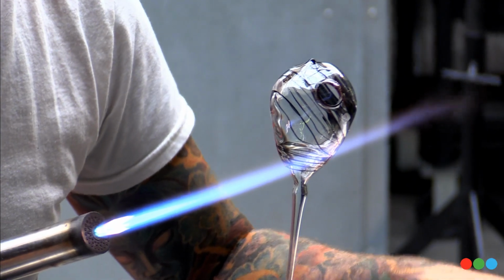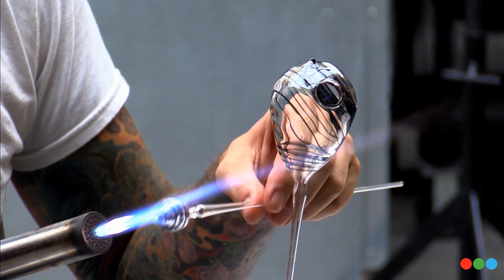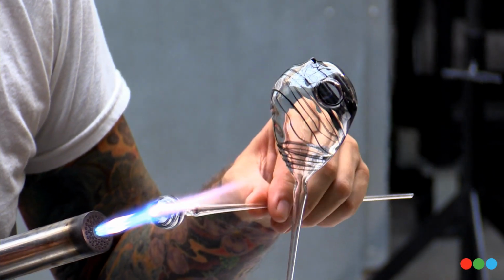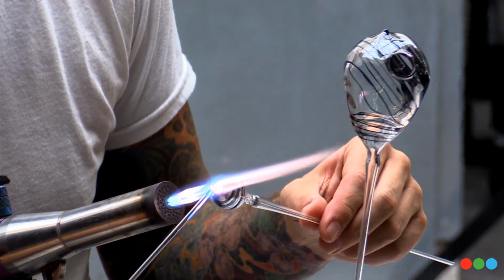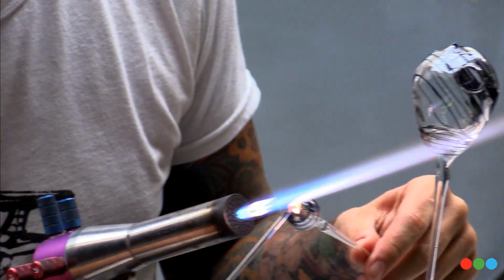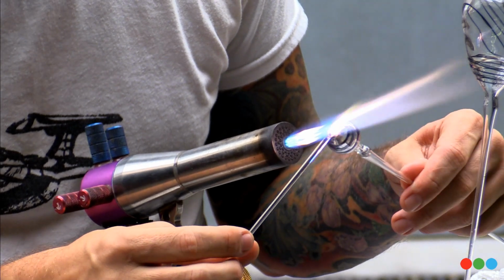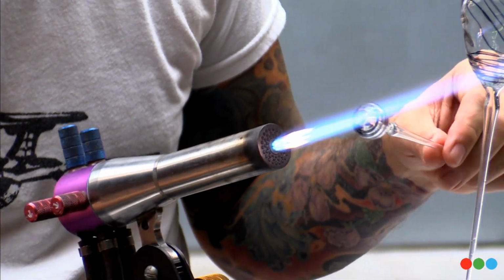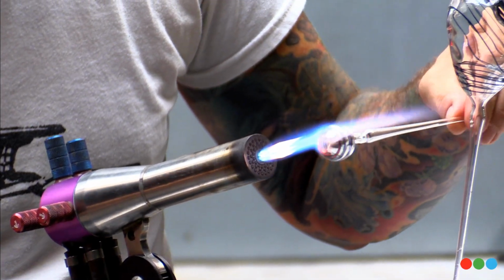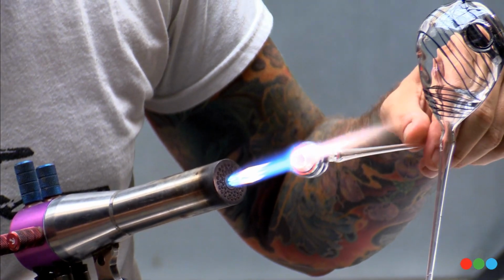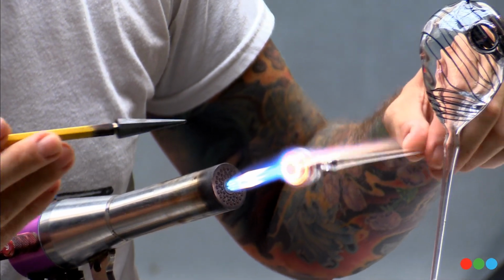So typically, and if you've ever seen one of our hot glass demonstrations over here, when we're making something, we're keeping the entire thing above 900 degrees the whole time, and then when we finish it, we remove it, place it into a kiln, and cool it slowly to room temperature. And the thicker the glass is, the slower we cool it. It's all based on its thickness.